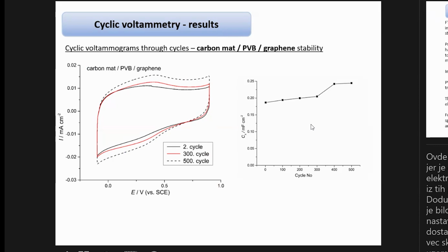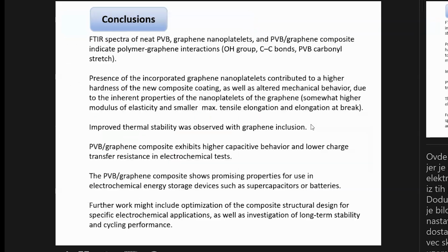In electrochemistry, as I told in the beginning, it is important to have high porosity and high specific area of the material. And in our composites, although we performed ultrasonic deagglomeration and had intensive mixing of the solution in the beginning when we prepared the material, some of the graphene nanoplatelets remained agglomerated, and over time, after many cycles, the electrolyte is penetrating between the agglomerates and reaching all the layers of the graphene. So this is why we have the increase of the current and the capacitance over time, that is, with a bigger and bigger number of cycles.